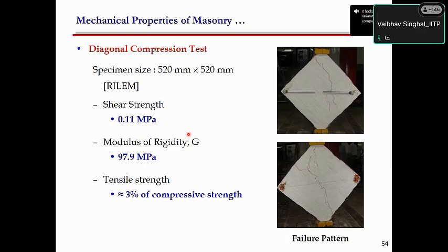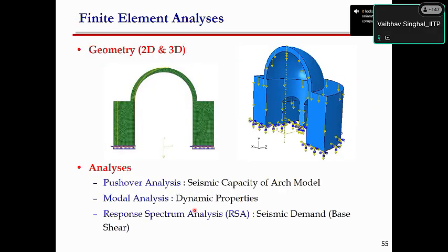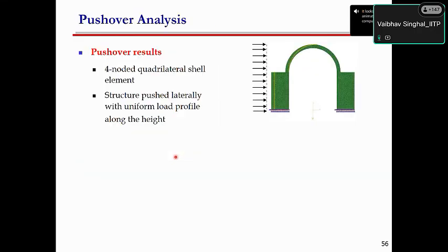This is a diagonal compression test, which is commonly used to find out the shear strength or tensile strength. The shear strength was found to be 0.11 MPa. So 0.11 MPa is found to be quite low for this type of masonry. Just remember this number, 0.11, we will see it in the analysis part. And the tensile strength is approximately 3% of the compressive strength. After finding out the properties, we have the elastic modulus and the compressive strength.